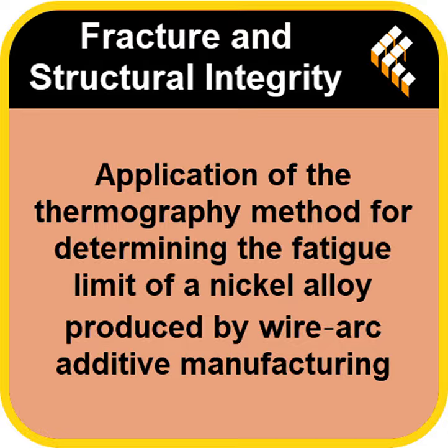Yes, so by watching that surface with a super sensitive infrared camera, the researchers can pinpoint the exact stress level where the temperature curve suddenly breaks or kinks and starts shooting upwards. That kink point, that is the fatigue limit. That is just such an elegant solution to a really massive problem. What kind of setup did they use to actually capture such a subtle heat signature?